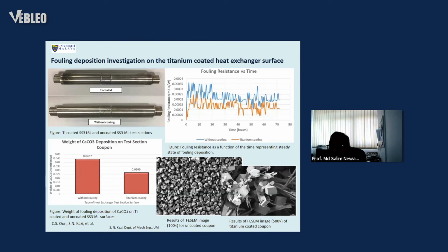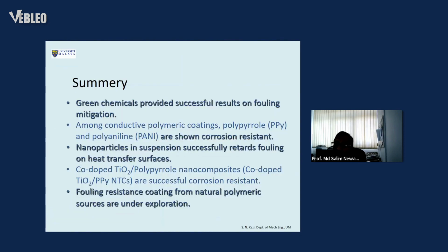There is another coating result shown here. In all the cases, we find that it reduces the deposition on the heat exchanger surface. Finally, we see that the green chemical additives provided successful mitigation, and among the coatings, the conductive polymeric coatings and the composites, which can keep the heat transfer resistance at a lower level while the surface deposition is retarded, can be developed with the procedures mentioned here. And with this, we move on further.